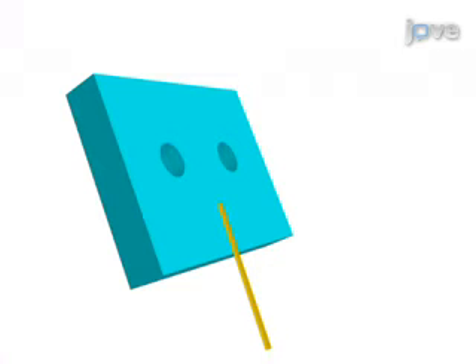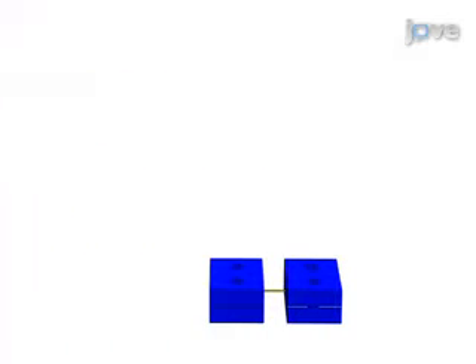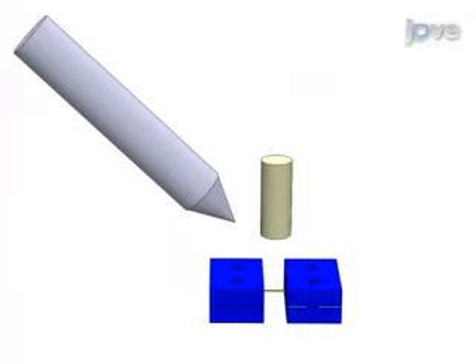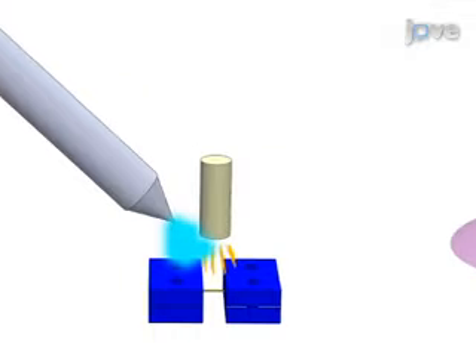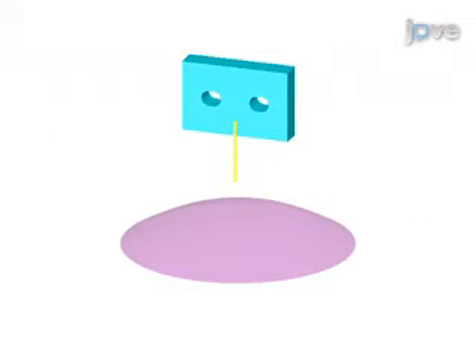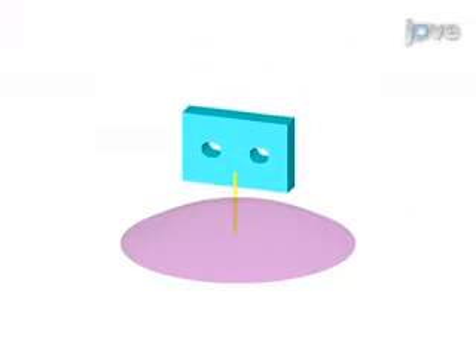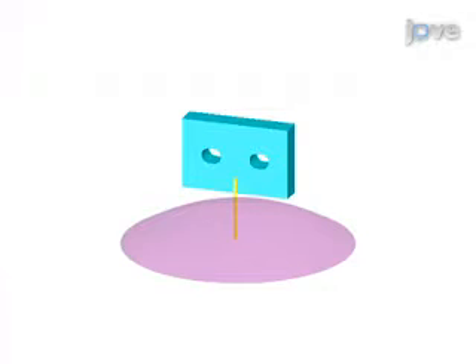This is accomplished by first patterning the polymer nanocomposite samples and adhering them to acrylic holders for insertion into tissue and micromechanical testing. The second step is to prepare a microtensile tester environment to mimic the physiological environment ex vivo using a humidity source and a radiant heat source. Next, the implant sample is inserted into tissue and removed after a specified duration.